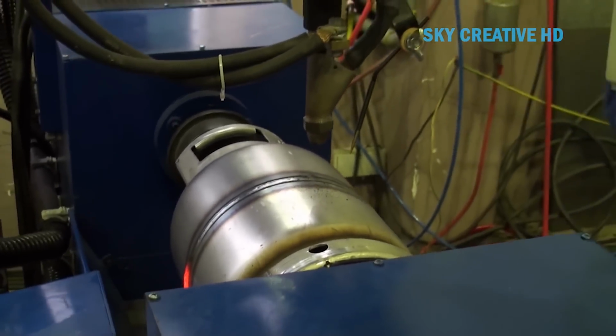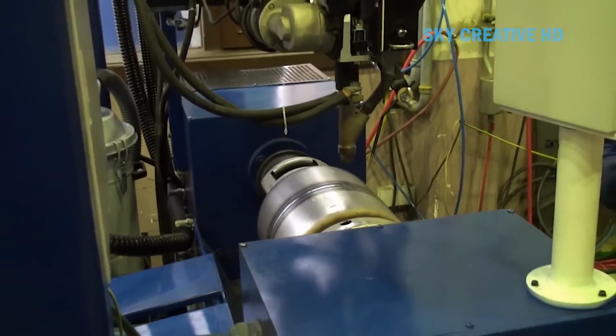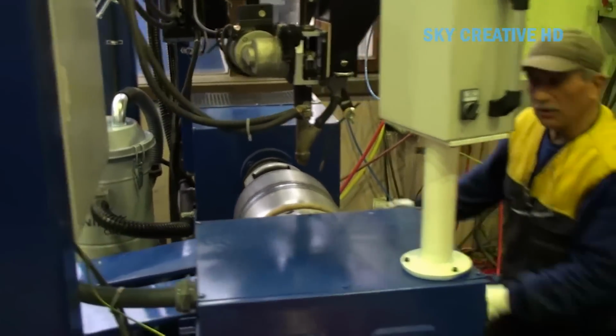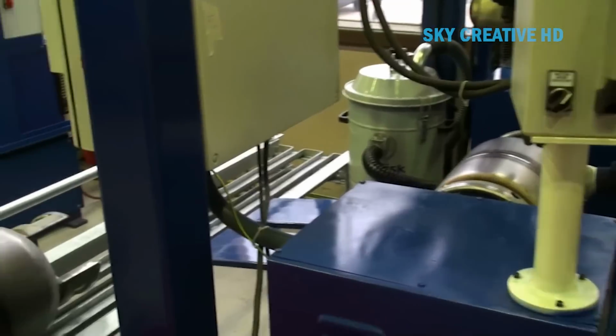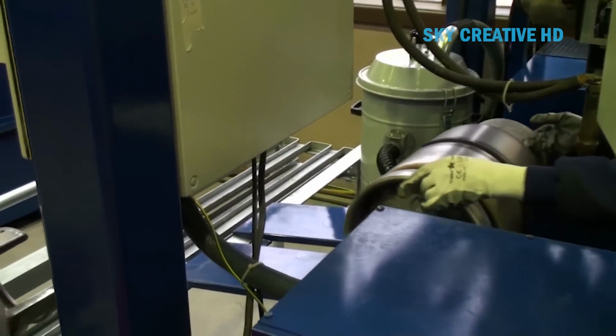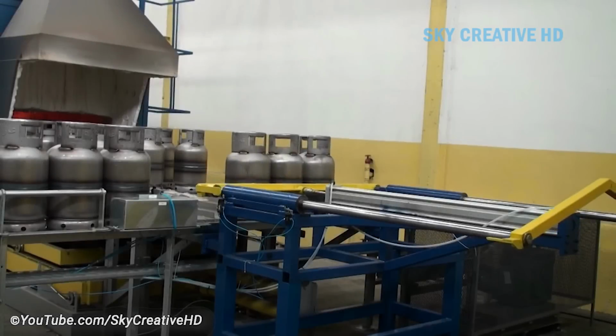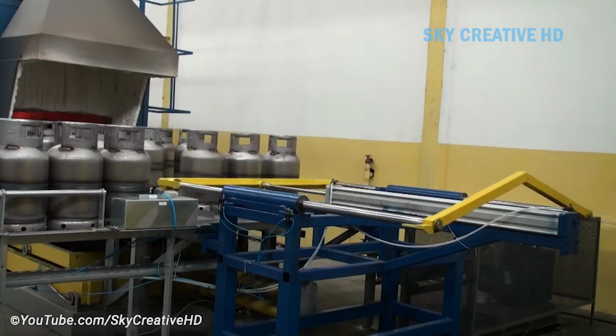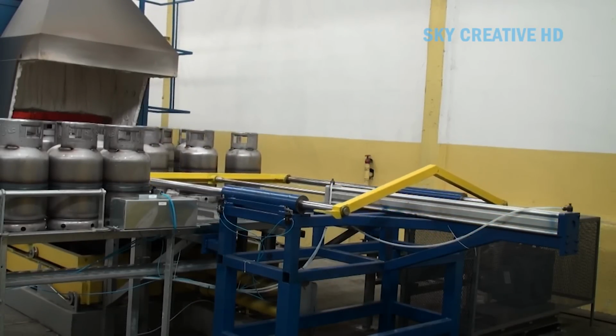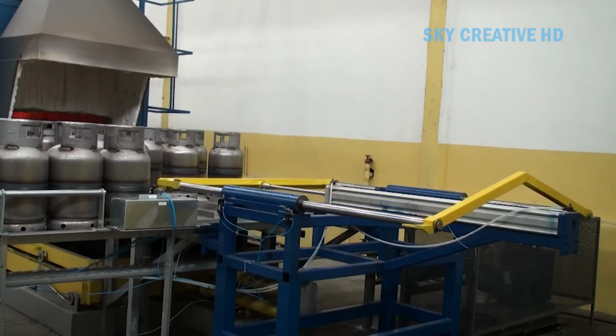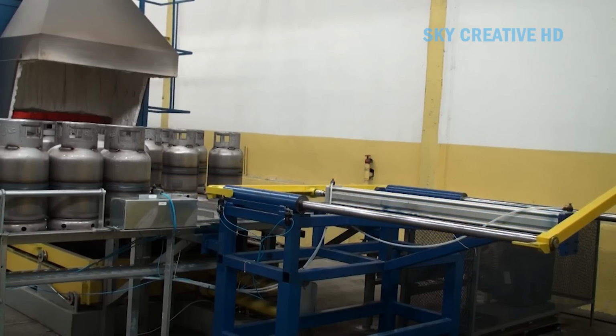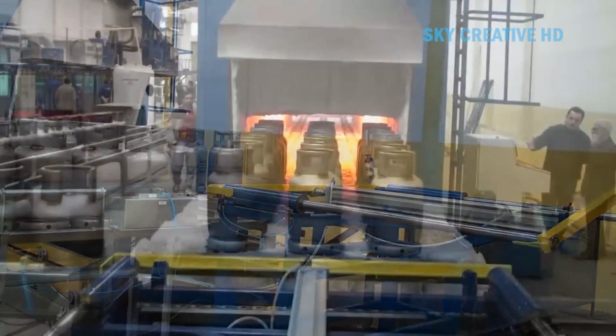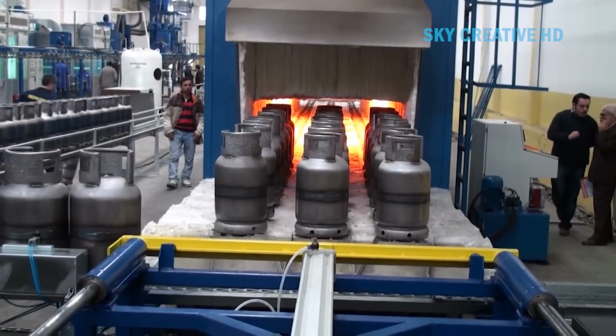Hydrostatic testing is a critical safety test where the cylinder is filled with water and pressurized to a level significantly higher than its operating pressure. This test verifies the cylinder's structural integrity and detects any leaks. Repkon provides automated hydrostatic testing systems that control the pressurization, holding time, and depressurization, ensuring compliance with relevant safety standards. The system also monitors for any permanent deformation or leakage.